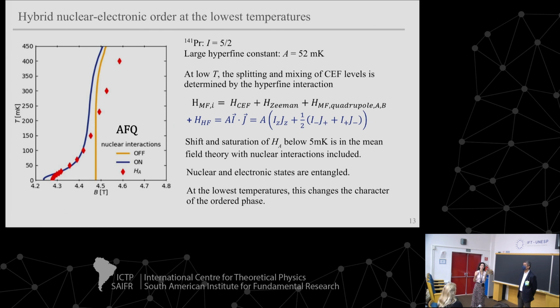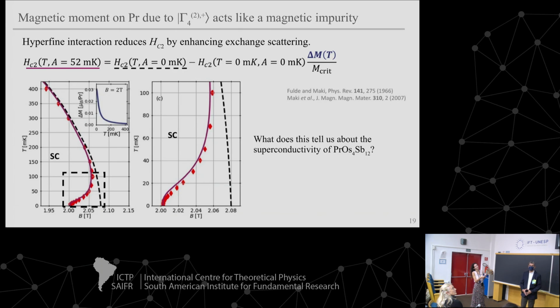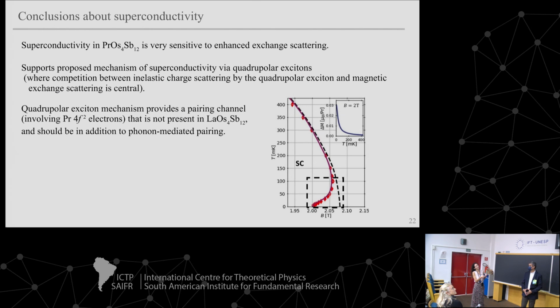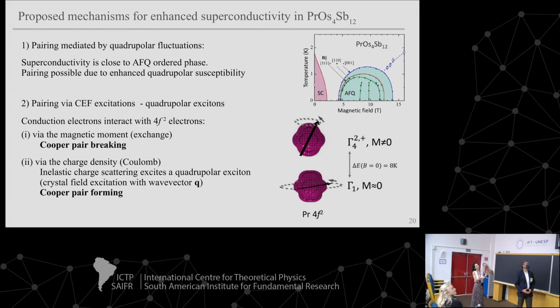People have measured with pressure at a higher temperature, and this also shifts the AFQ to slightly lower magnetic field. So when this phase boundary is enhanced, this should enhance the quadrupole susceptibility, and you would expect this to enhance superconductivity. That scenario is also thrown out the window by the pressure experiments, because pressure moves the AFQ phase to lower field, but it doesn't enhance the superconductivity in that case either. So with pressure we would expect maybe not to change the temperature dependence, but to shift everything again to lower field.